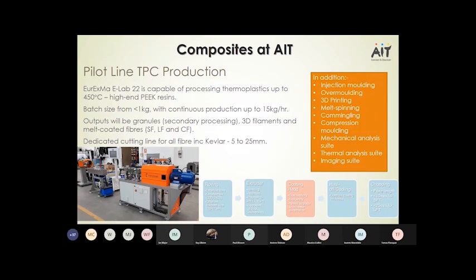On the line, we can process small batches, less than a kilo, up to 15 kilos an hour. We can make granules for secondary processing, such as injection molding and over-molding. We can make 3D printing filaments for standard fused filament fabrication. And then we can have different melt-coated fibers: short fibers, anything below 5 millimeters, long fibers, usually anything below 25 millimeters, and continuous fiber. We have the ability to process a host of fibers, glass fibers, carbon, as well as Kevlar, and our cutting line is capable of cutting Kevlar.